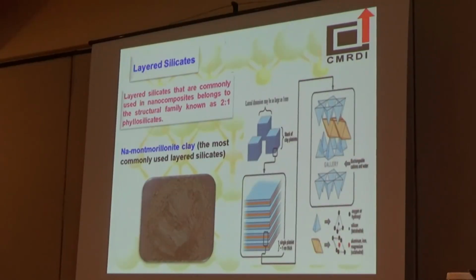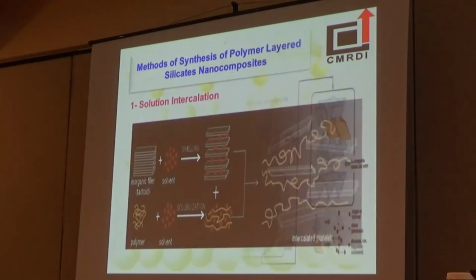And the reinforcement added in our study is layered silicate, which is one member of the smectite clay family, and it belongs to the structural family known as 2-to-1 phyllosilicate. Each clay particle is composed of hundreds or thousands of layers stuck to each other by weak van der Waals forces, and they are separated by interlayer spacing containing exchangeable cations. The thickness of each layer is about 1 nanometer. To obtain the nano-sized layered silicate, we have to separate these layers from each other.